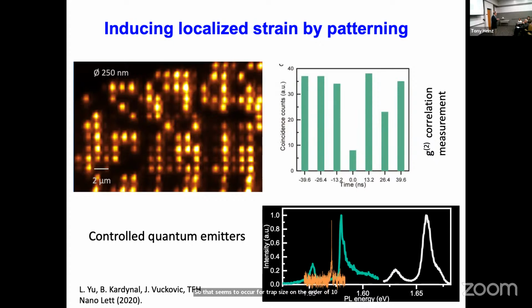From the experimental point of view, the part that's a little bit tricky is not making a very small dip. What's very nice about this is that you don't have to have a perfect topography to get a trap. Of course, it'll change the profile of the trap a little bit, but it's not like trying to chemically modify the sample, where if one dopant is not quite in the right place, it's going to make a huge difference.